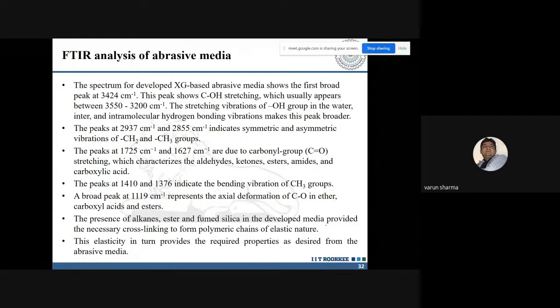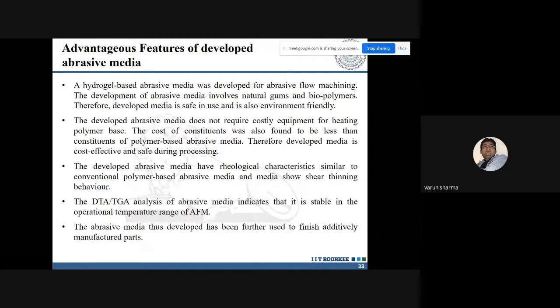Now this elastic nature is one of the desired properties of the abrasive media, because it gave it the desired deformable characteristics so that it can get the desired surface. The advantageous features of this particular abrasive media is that it is stable for the operational temperature range for the AFM. The viscosity of the abrasive media was higher than that of the conventionally used media. Whether you are going to get a desired finish in titanium or relatively softer materials like ABS or PLA based material, this particular abrasive media can be used.